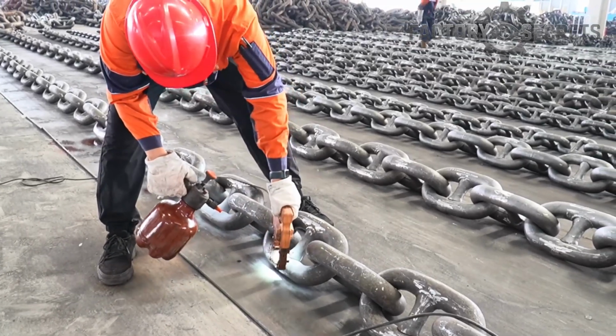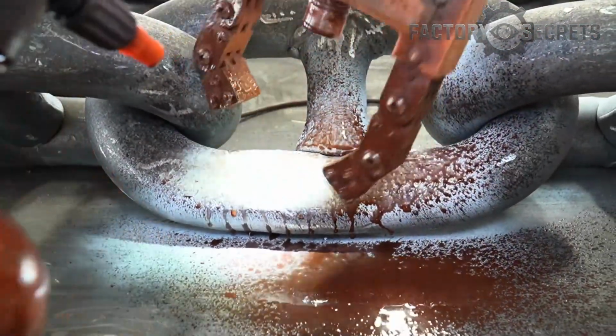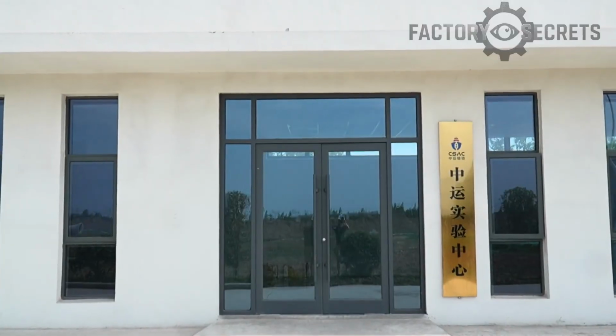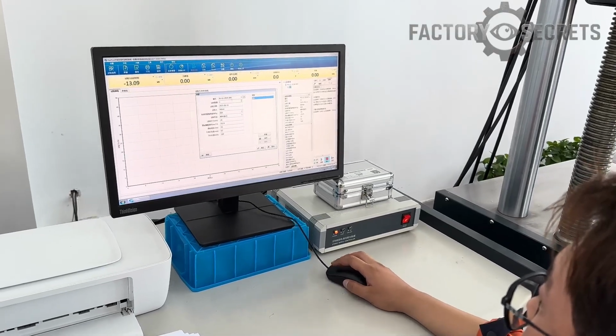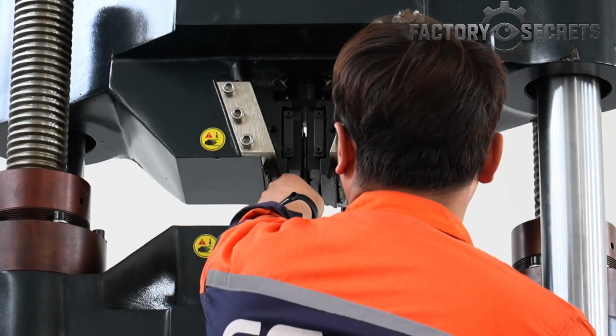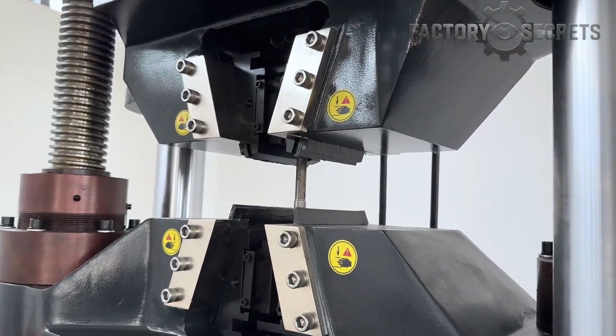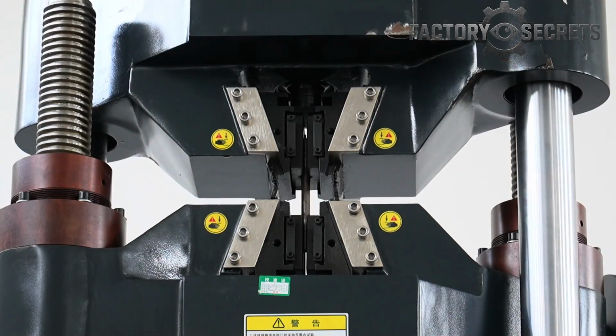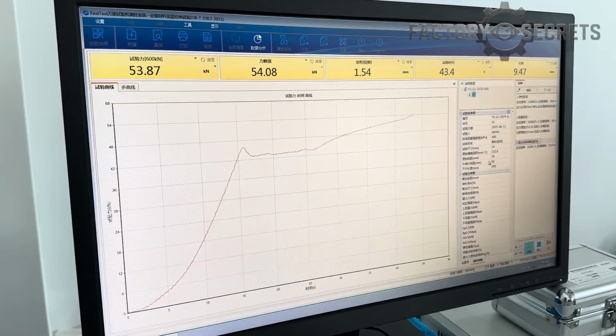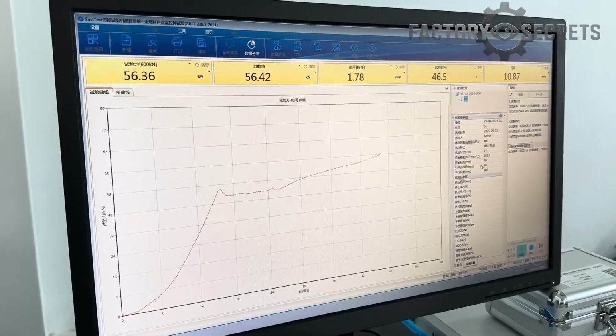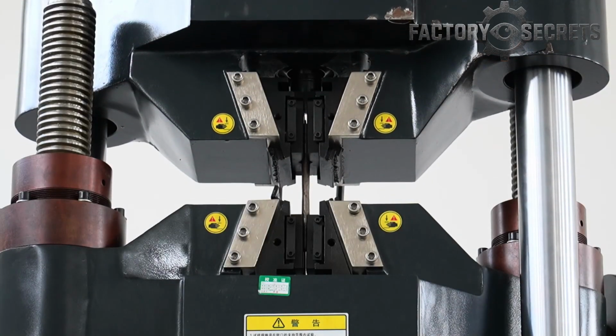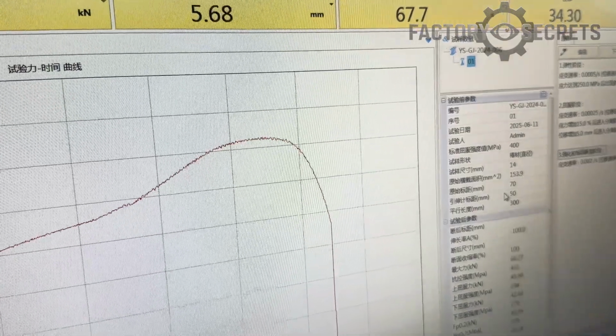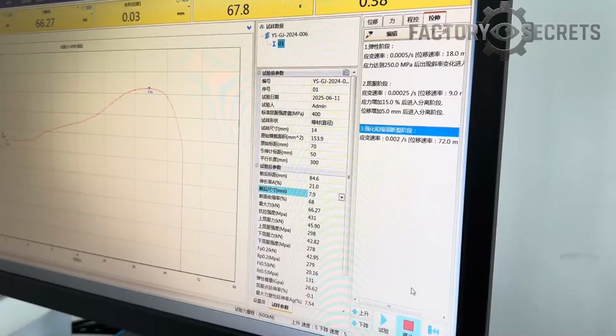The inspector then uses a specialized probe connected to the inspection console, scanning methodically across the chain. The graph on the unit tells the story the human eye cannot see. The final stage before coating is mechanical verification, conducted not on the chain itself, but on a sample rod from the same material batch. In the testing lab, a small specimen is prepared and placed inside a precision tensile testing machine. The machine pulls the sample apart, slowly, measuredly, recording every data point as the steel deforms and ultimately breaks.